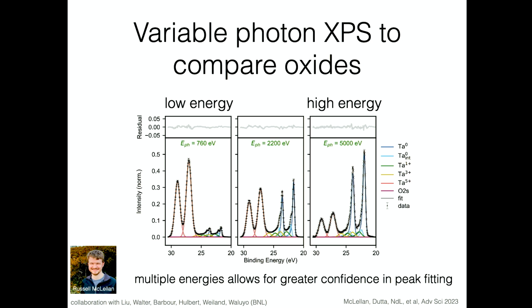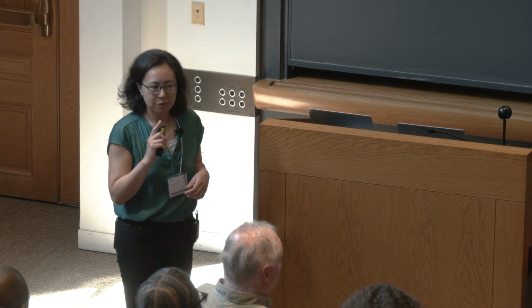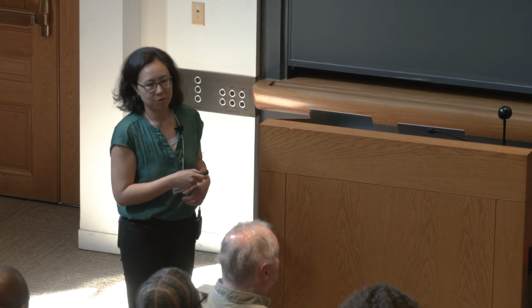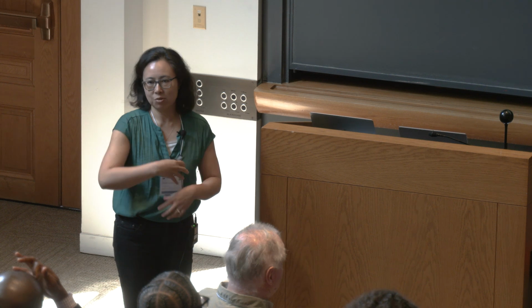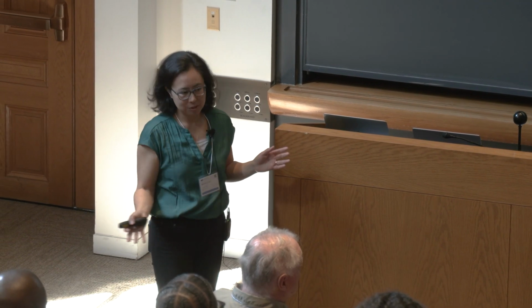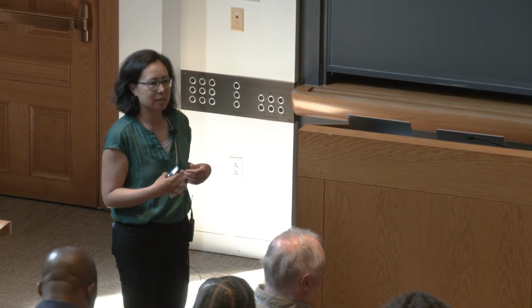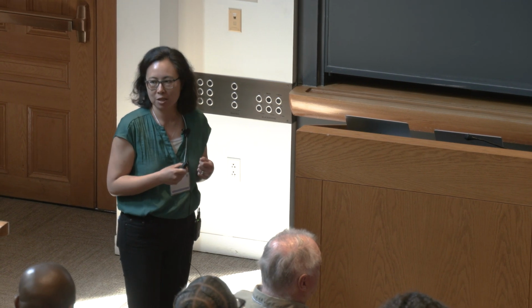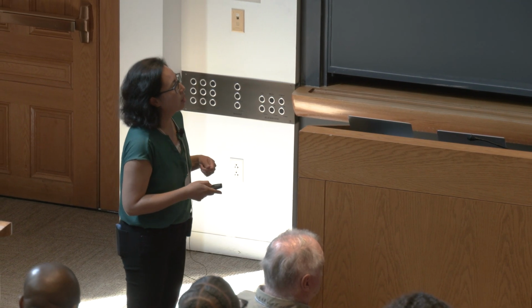So I'm now a little bit of a convert. The key thing is that there's a weird data science flavor here. I'm taking all of these different energy shots, and this is 3 of like 20-something that we did, and all of them come from the exact same material stack. So again, I can simultaneously fit the entire data set. And what I know is that all of them had to be looking at the same oxide stack. So I know now from a statistical standpoint, this is the correct number of peaks. If I add a peak, my chi-squared blows up. If I subtract a peak, my chi-squared blows up. So by using these data science tools, we're able to get access to more information than you would if you just naively fit the data.